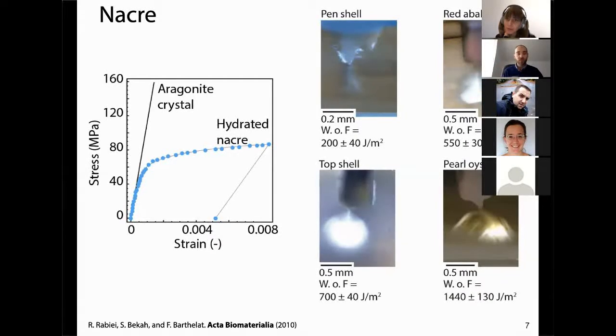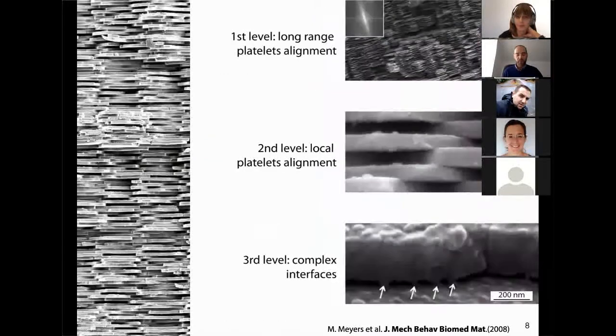These white zones are where the microstructure is working very hard to stop the propagation of a crack. You can reach plastic zones or zones of damage that are extremely large for something that is 95% a ceramic. The reason why we seem to have these very diffuse damages has been studied for a very long time, and nobody exactly knows which part is most important, but we know that there are several levels of hierarchy in the microstructure.